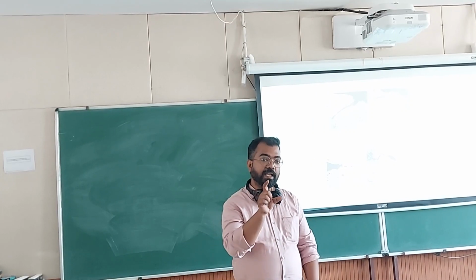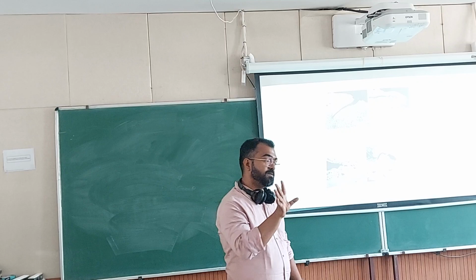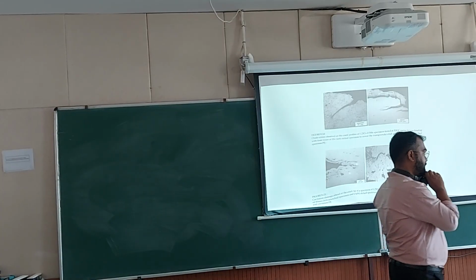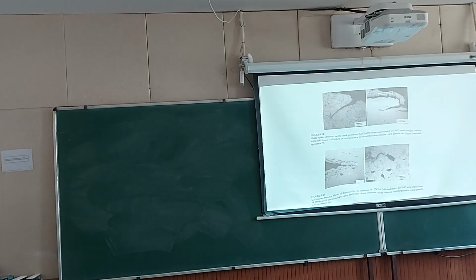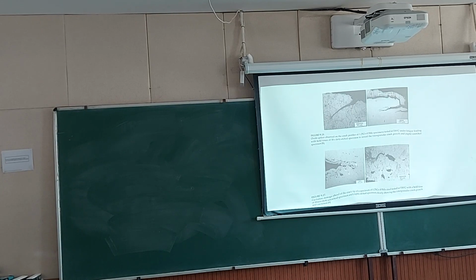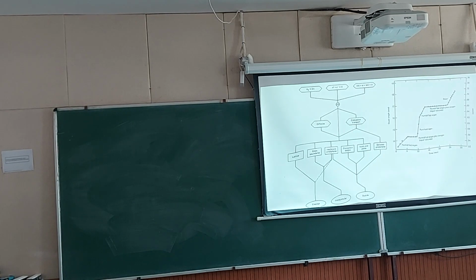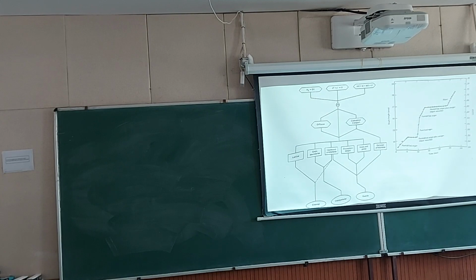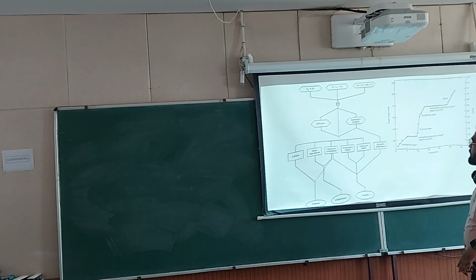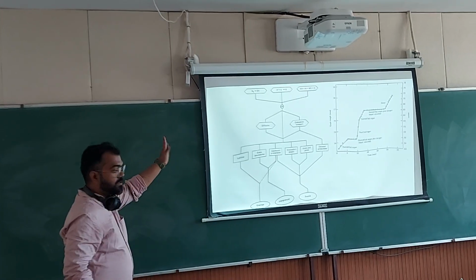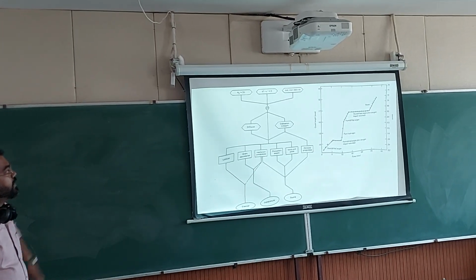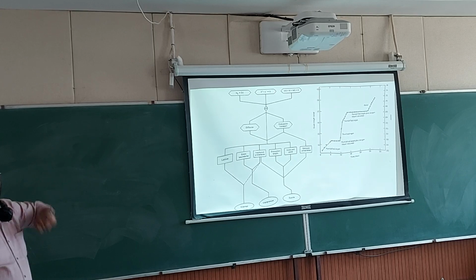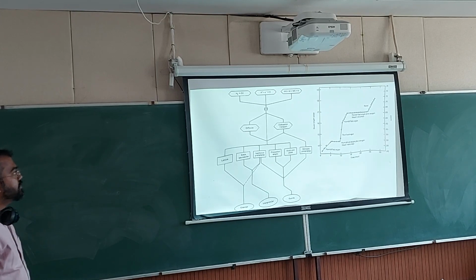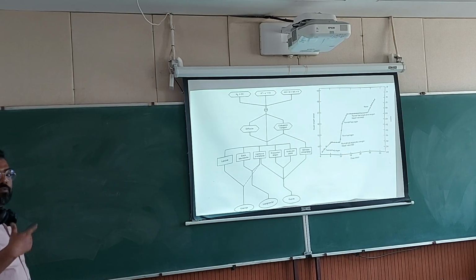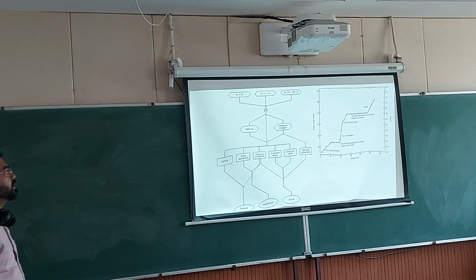So something will take away this oxide. So this has been observed that when oxide formation happens, then the crack resistance decreases. So before that, let us look at this hydrogen thing. So hydrogen can change to atomic hydrogen, okay, via different processes. So it can lose one electron or it can join with one electron. Both of these things it can do.